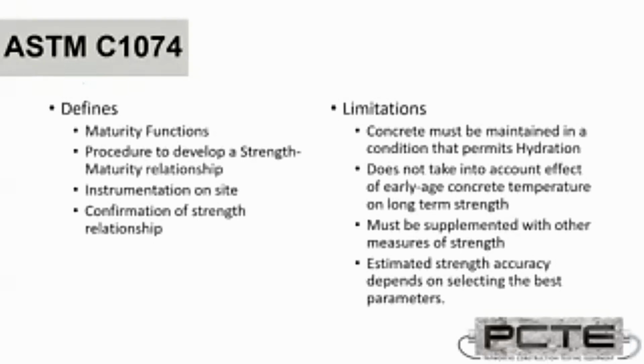A couple of very big limits that it makes very clear in the standard is this technique assumes that concrete is maintained in a condition that permits hydration. What do I mean when I say that? I mean that the concrete needs to have the chemical reactions continuing. If it gets too cold, or if there is insufficient, sorry, not too cold, if there is insufficient water to allow that chemical process to occur at its natural pace, you will overestimate strength gain. So if your concrete is not properly cured, your maturity relationship will not follow.